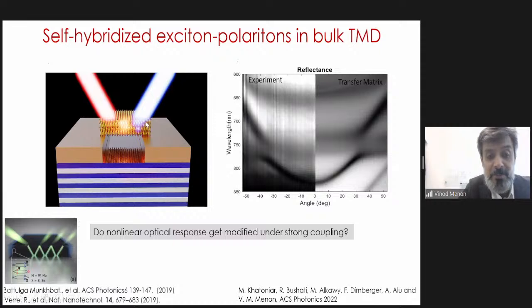So we take this material, we create this high refractive index material, and then we put it on top of a mirror here. We have an air gap and all of that. And you can see that you can get nice strong coupling just between the light that is coupled inside and the excitons that are inside the system. So you don't need a cavity for this particular experiment.